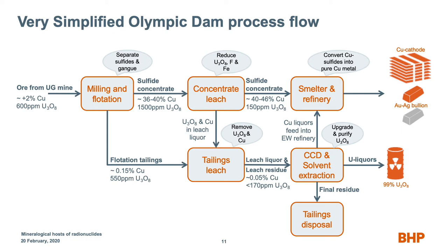So we'll jump very quickly to an incredibly simplified flowchart for Olympic Dam. Ore comes in, grinding and flotation, you make a sulfide concentrate. The sulfide concentrate does have uranium in it. We have a concentrate leach, and that concentrate leach extracts 90% of that uranium out. And that concentrate goes to the smelter. The concentrate, sorry, we'll back step for the float. In the float tailings, that's where the bulk of the uranium goes. It ends up in tails leach, where we do a sulfuric acid leach and extract the uranium out of there. But the uranium that goes into solution up in concentrate leach also goes into tailings leach, CCD, solvent extraction, make uranium, and out we go. We're interested in the fate of uranium and the radionuclides up there.